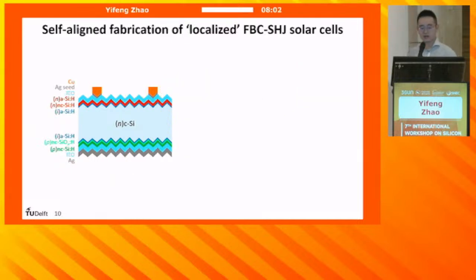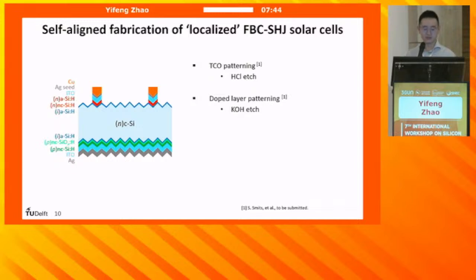So in our group, we developed a self-aligned fabrication process that utilizes the metal contact as the etching mask. So here, we pattern the TCO using hydrochloric acid etching, and then we etch the doped layers, namely the amorphous silicon and nanocrystalline silicon, by using potassium hydroxide etching. However, there is almost no etching selectivity between the N-type layer and the intrinsic layers. So therefore, the intrinsic layer will also be removed, and repassivation is needed. But if we look at the device, we have copper electrodes that are already there, so it's not easy to repassivate due to the copper electrodes.